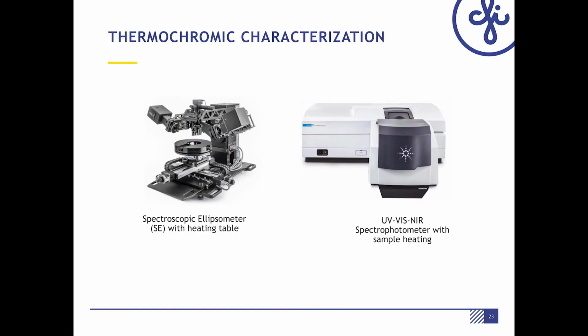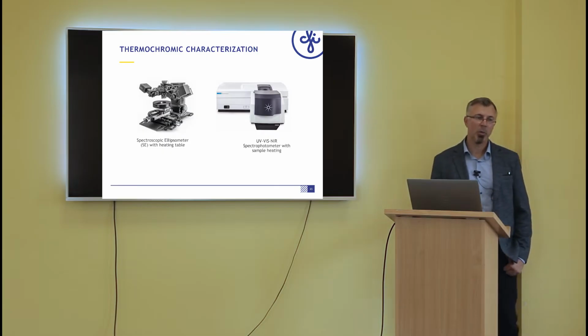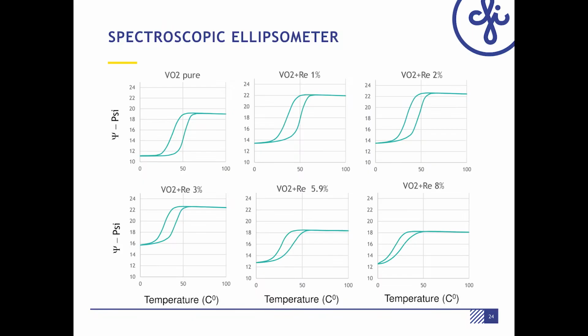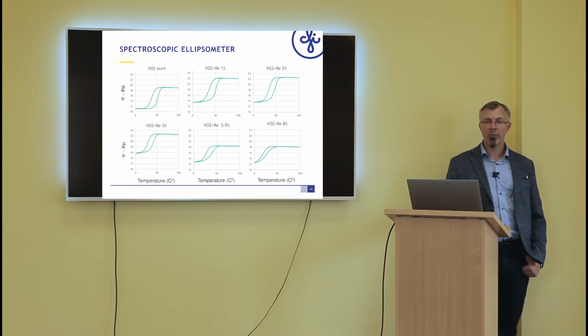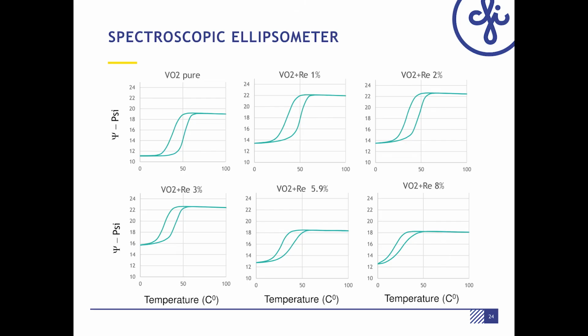Spectroscopic ellipsometer with heating table and UV-VIS-NIR spectrophotometer with sample heating can be used to characterize thermochromic thin films. Spectroscopic ellipsometer give us a possibility to see how doping of rhenium in this case shifts phase transition temperature. So on these graphs you can see that with increasing amount of rhenium, phase transition shifts to lower temperatures.